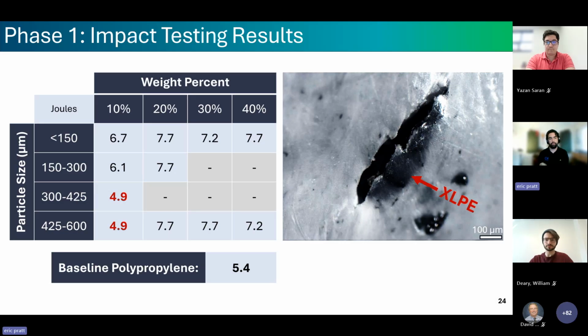For our composite, once we introduced our particles at the 10% loading, we saw a significant drop off with increasing particle size. So at our smallest particle size of 150 microns, we were still slightly above the baseline. But once we got up above 300 microns, we fell down to 4.9 joules. However, once we increased our loading up to 20% and above, that difference caused by particle size started to disappear. And once we were above 20%, between 20 and 40 within our particle size range, there wasn't really any statistically significant difference caused by particle size or increased loading.